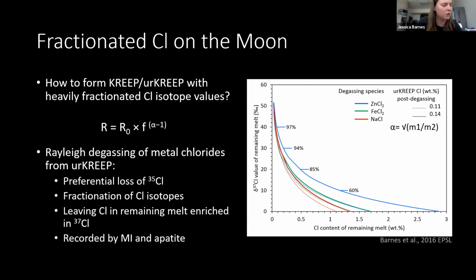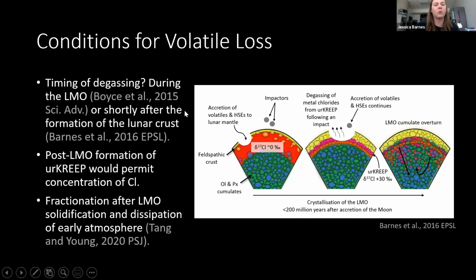But when did this degassing or volatile loss occur? So we've already established that urKREEP likely has very fractionated chlorine. So it had to happen either during the lunar magma ocean, with degassing from that magma ocean, or shortly after the urKREEP reservoir had formed. In our 2016 paper, we argued that the latter is more reasonable because you have to concentrate the chlorine before you lose it. And not just that, but early on in the moon's history, while the lunar magma ocean was solidifying, there would have been an atmosphere around the moon. And so that would have prevented the loss of chlorine from the system. Any chlorine lost to that atmosphere would likely have rained back into the magma ocean and been mixed in again, canceling out any fractionated chlorine isotope signal.